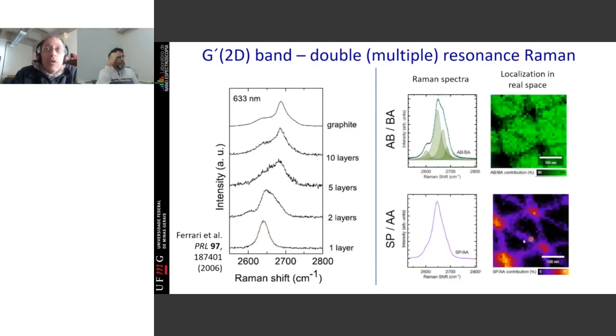And when we now do this locally with our nano antenna, this is 100 nanometers, you see that this kind of line shape, which represents 2 layers, specifically 2 layers with AB stacking, is exactly on the region where we were induced to say that this was the AB stacked region, AB or BA. And when you look at the strain solitons, the line shape changes completely. This is the line shape that you get in these regions, because the electronic structure and the phonon structure at these locations, at nanometer resolution, are different.